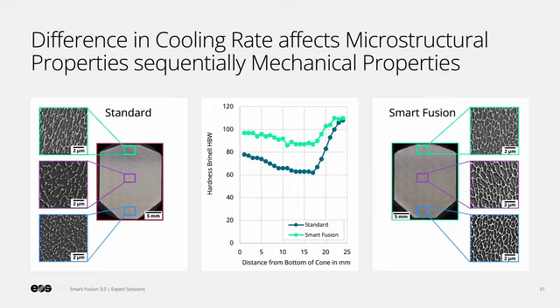Here in this slide, we see two samples, one built with standard process parameters and the other using Smart Fusion and laser power adjustment. On the left side, if we take a look at BSE images taken from different positions of the part and compare silicon-rich phase morphology, we see a strong dissolution of the silicon phase and a drastic change in morphology from network shape to coarse large particles in the sample built without Smart Fusion.